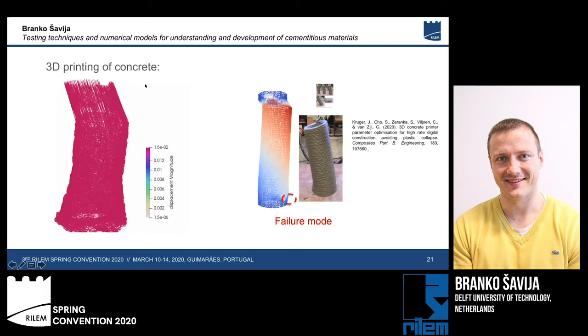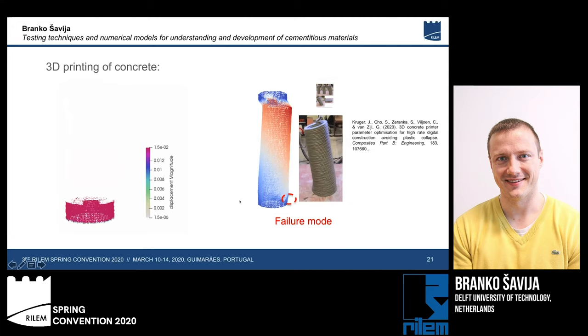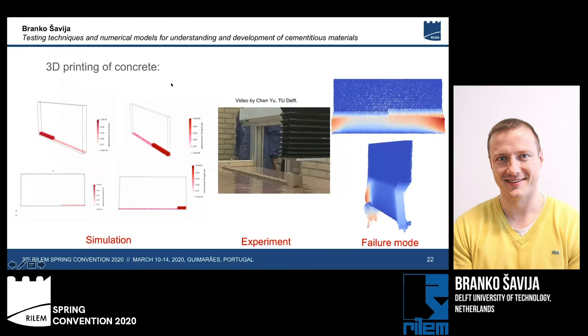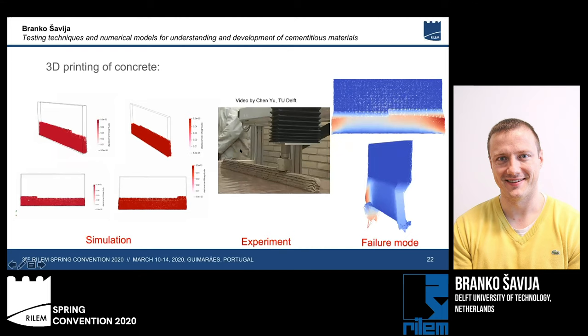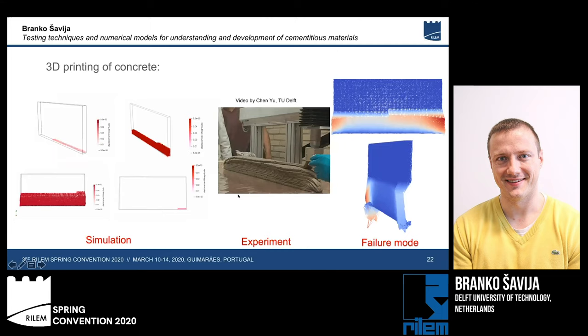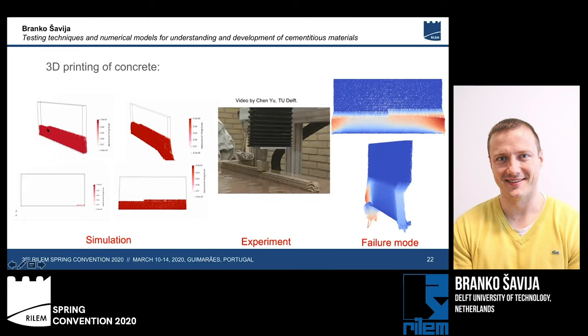A similar thing is shown here on the right-hand side. And this is a typical example of plastic collapse, as seen here in experiments from this publication. And our model is qualitatively already able to predict that. Now, the other failure mode, the elastic buckling, is also very important, in which we add layer upon layer of material, as we see here in this experimental video. And because the situation is not completely symmetrical and the load is not centric, the material just falls on its side. And our model can already predict this type of behavior.